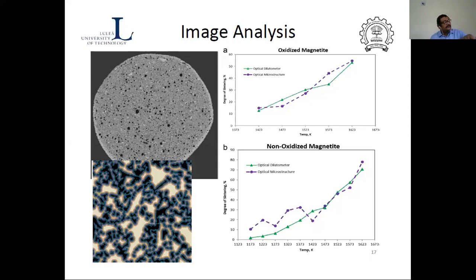So we saw that what we physically observed by shrinking can be correlated. See, this is the optical dilatometer. This is from the microstructure. How beautifully these two can be correlated. So that way, how a macroscopic observation can be correlated to a microscopic observation, that too in a quantitative fashion, is what we could establish through this analysis.